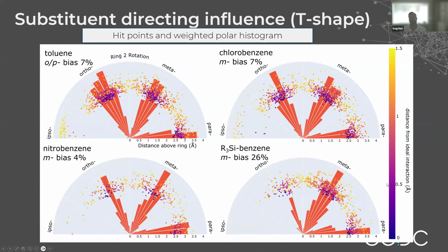So one final piece of information you might take from that large data set is the substituent directing influence. So looking at T-shaped interactions here. If you remember from, I don't know, first year undergraduate chemistry, we have toluene. So this is a benzene with a methyl group replacing one of the protons, and that tends to be para-directing in terms of how it reacts, because there is electron density pushed to the proton directly next to where the methyl is, and directly opposite, so that's also in para. And you can see a very small bias of 7% for the case of toluene, which is probably not really that statistically significant.